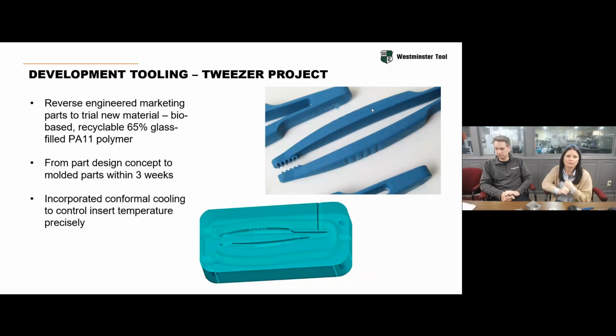They actually just gave us a concept. They said, hey, we want something like this. It wasn't even this actual pair of tweezers. From design to molding 2,500 parts for them, it took us about 3 weeks. You're not going to be able to see well, but we did not touch the actual part geometry on these parts. We only squared up the block and put in ejector pin holes. I'll show you in a moment. But I did want to point out that in the bottom picture, you can see that we also put in a contoured cooling line, and we utilized an extra plug hole in the back just for easier access for cleaning that U shape if needed.